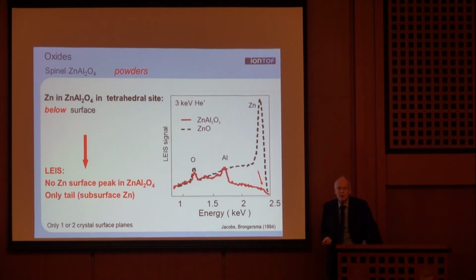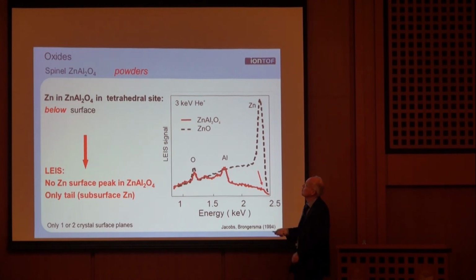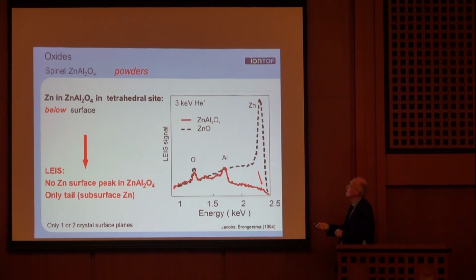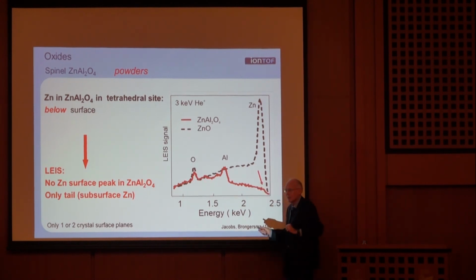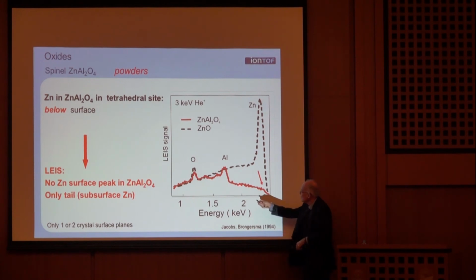Spinels and perovskites are important mixed oxides that are used for many applications. I'll first show you something on spinels. They have the structure of, say, AB2O4. For instance, zinc aluminate. And when you do the ion scattering of a zinc aluminate, well, this is an old spectrum, so the statistics is not so good. Nowadays we do much better. But you see an oxygen peak, you see an aluminum peak, you see a background here, but no peak.